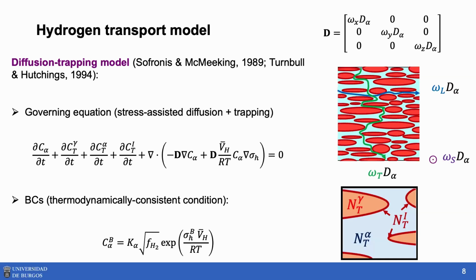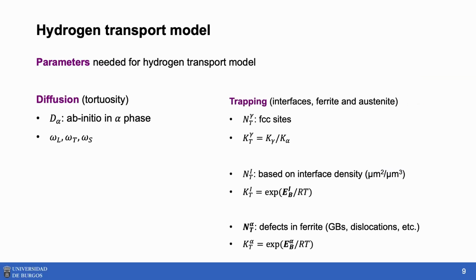I also want to mention that you have to be thermodynamically consistent to model your hydrogen uptake. So you can use a kind of Sieverts' law, but using fugacity and including the effect of hydrostatic stress on this uptake. We have a lot of parameters, but it's easier than it seems.